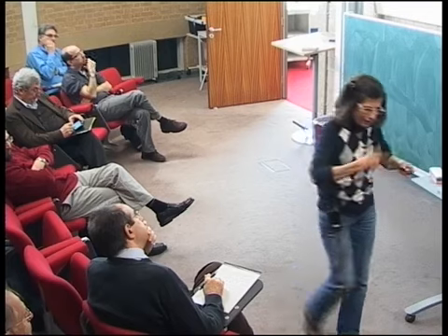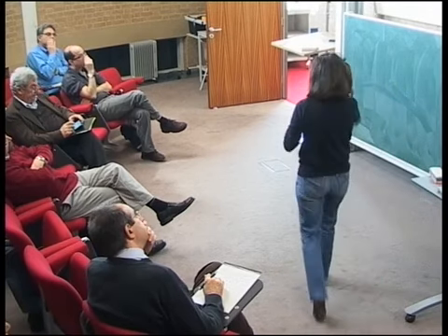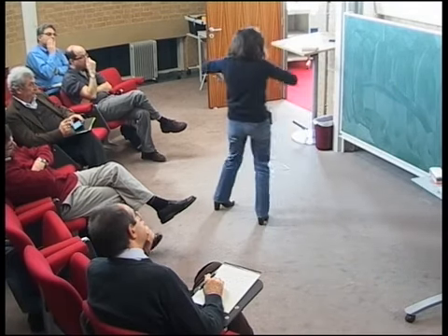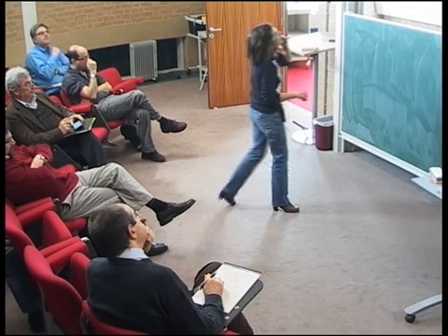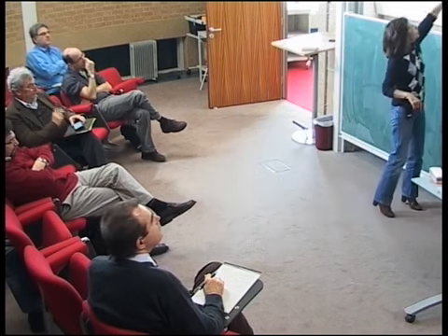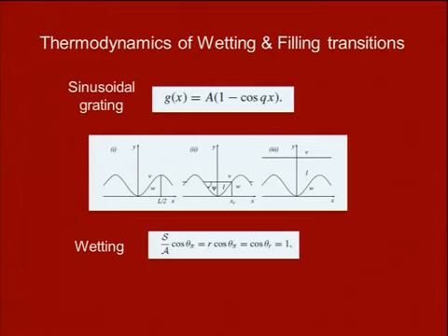By contrast, if the surface is like Teflon and it doesn't like the fluid, then roughening it enhances the drying effect. So there is an extra bit that comes just from the extra surface. And if you define the apparent contact angle, then you can say that this is where the wetting transition will occur if you only take into account the excess area.